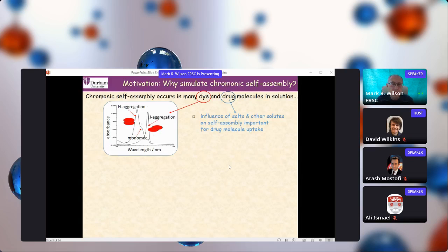For example, if you get direct stacking of molecules on top of each other, we call that H aggregation, you tend to get a blue shift in the absorbance and very often a very broad absorbance arising from the aggregation. But sometimes when you get shifted aggregation, we call that J aggregation or Jelley aggregates after the guy who discovered this, you get a very sharp absorbance band which is usually shifted to the red. So how these things aggregate in solution is actually rather important. Understanding that is quite an interesting thing to do for dye molecules.